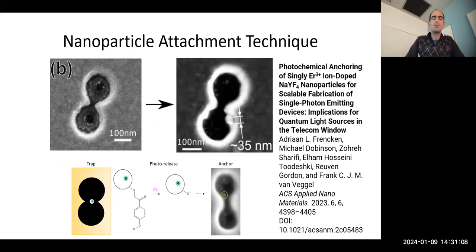One approach that Frank's group came up with, Adrian came up with, was a surface chemistry that could be photocleaved. We would trap a nanocrystal, and once we decided this was the one we wanted, we would apply ultraviolet light, which would cleave off part of this ligand and expose a thiol, which would then attach to the gold.